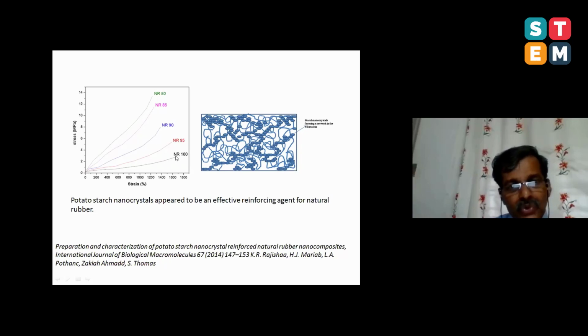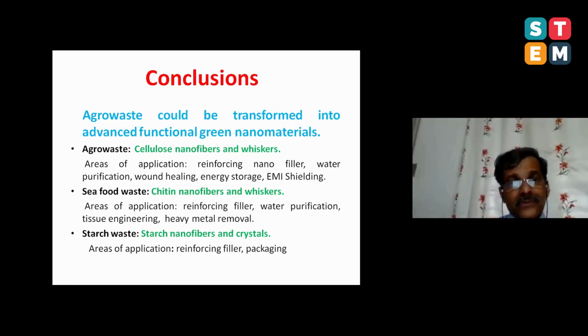The strength is maybe 2 or 3 megapascals. If you put 20% of nanostarch nanocrystals, look, the strength goes to 14 megapascals without sacrificing ductility. Still, the material is extremely ductile, more than 1000% ductile. The modulus goes up. So we were able to make a very strong natural rubber nanocomposite material by putting nanocrystals extracted from potato starch waste. And finally, I wanted to conclude that agro waste that you get from the agricultural land could be transformed into functional green nanomaterials.